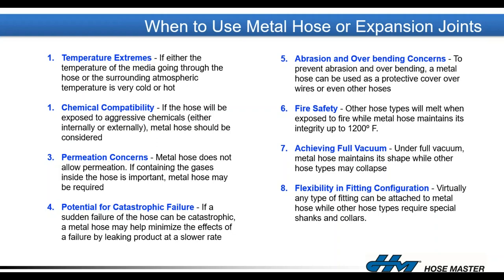Also, metal hoses can be used where abrasion or overbending are concerns by adding that strip wound either internally inside the hose as a liner to protect those corrugations from abrasive media. Also, that strip wound interlocking hose can be installed on the outside of that assembly to protect the hose from external abrasion or to protect it from being overbent. Because metal hose is made out of all metal, metal hose, metal fittings, metal braid, welded together with metal filler rod, they're excellent in applications where fire safety is required. Obviously, non-metallic hoses have temperature limits and they are vulnerable to melting or deteriorating under a direct flame, whereas metal hose maintains its integrity in those applications.